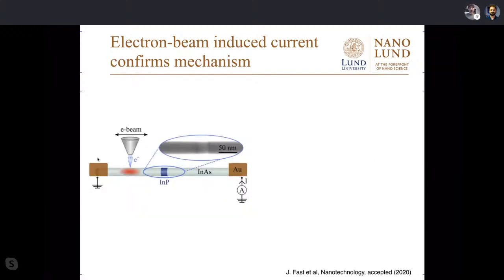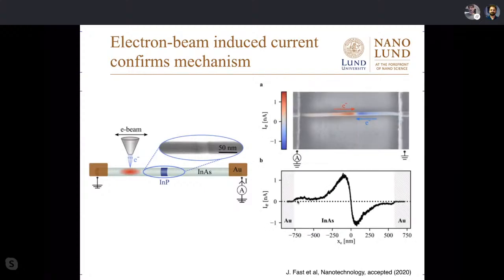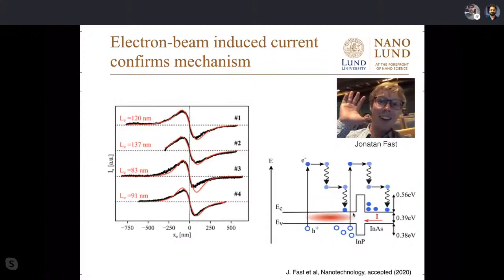This was important because people who know something about contacts and Schottky barriers that can happen at contacts were worried that maybe everything we see actually happens at the contacts. It's just some dirt effect. But that's clearly not the case. We don't see any current generation at the contacts at all. It happens around the barrier. We know that our barrier is there.